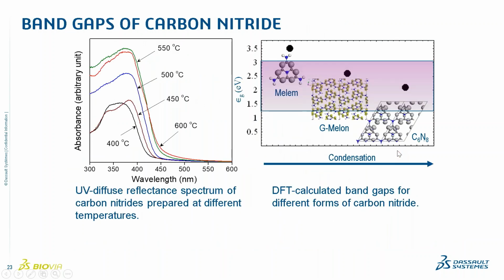In experiments, they have determined the band gaps as a function of the condensation level, so along this condensation path, and it indicates that the band gap is decreasing depending on the synthesis temperature, which is also indicating that the longer and the higher the temperature, the more condensed the material is.